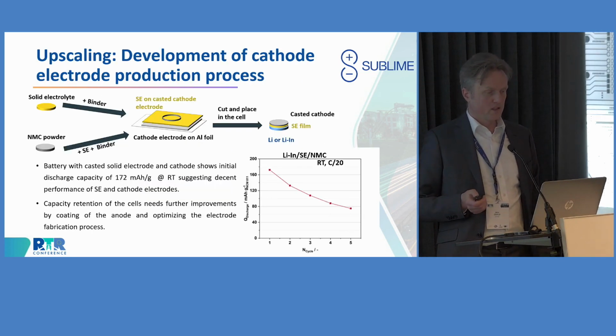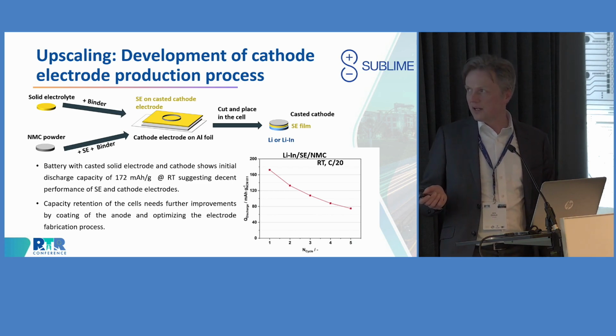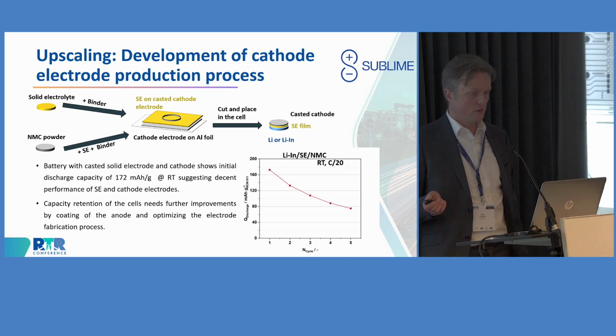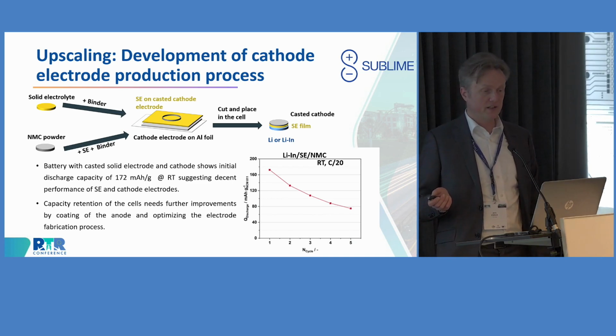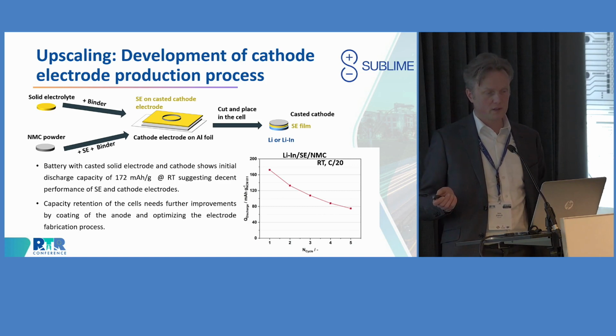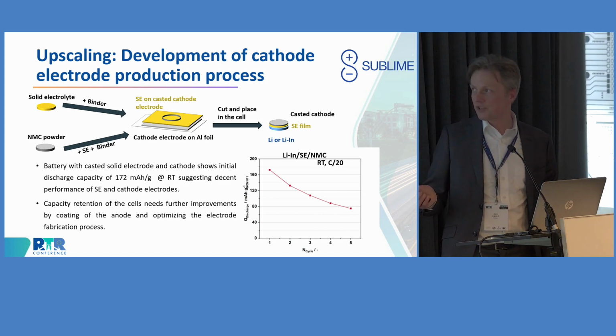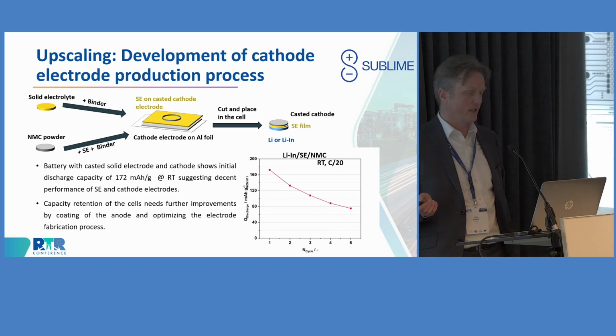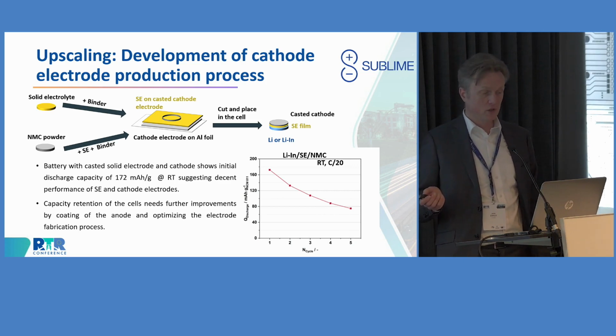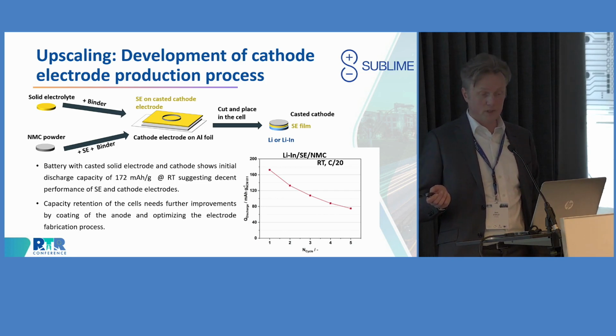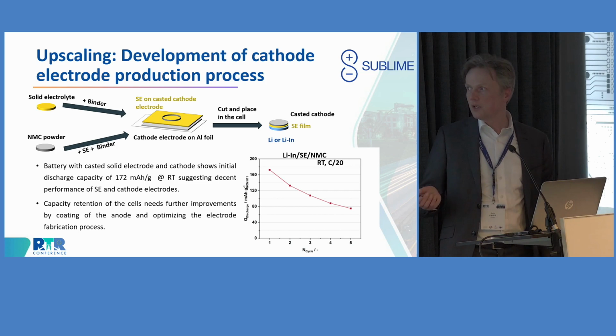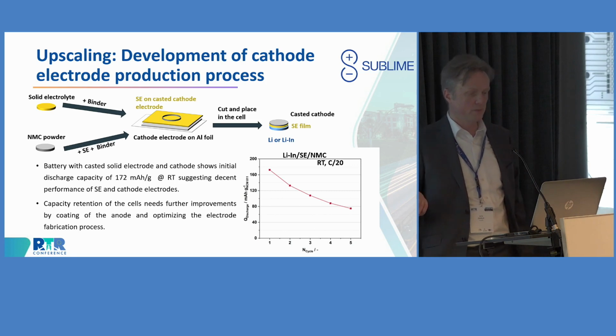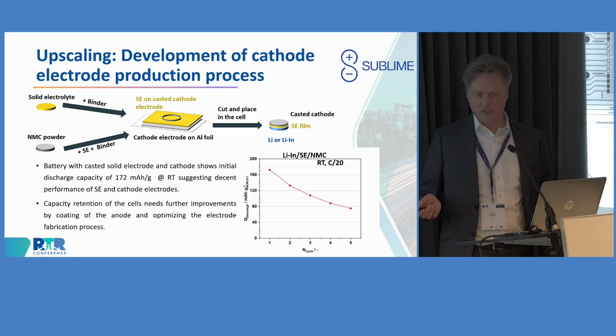So while we are still further optimizing the electrode on the anode side on the coin cell level, we can then further proceed with working towards the pouch cells with regards to the solid electrolyte and the cathode processing. So this is also being done and it's working. We see already here that we are able to reach a very decent initial discharge capacity. Maybe you remember that I showed 195 milliampere hours per gram of active material before, so that's just slightly below this. So next technology brick, we can further optimize.